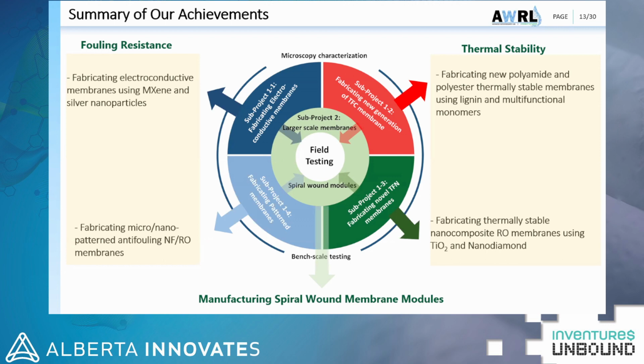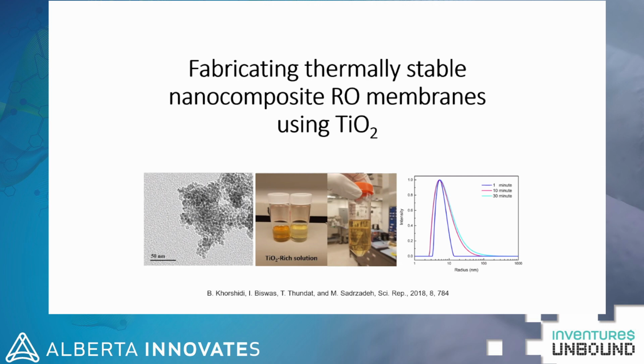Since we might have an audience from academia, I present some scientific aspects of fabricating thermally stable membranes that might be somehow boring. I start with fabricating nanocomposite RO membranes using TiO2. The main challenge in making nanocomposite membranes is the aggregation of nanomaterials and their incompatibility with the polymer matrix. The non-selective voids at the interface of those aggregates and the polymer reduce the selectivity of the membrane significantly. In fact, those aggregates in the polymer may cause rupture of the thin polyamide layer in TFC membranes.